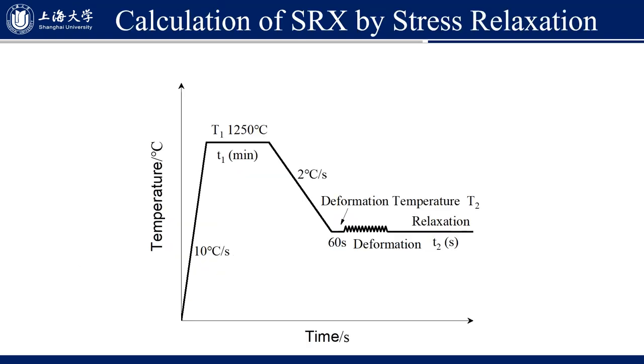Then let's discuss calculation of static recrystallization by the stress relaxation method. This slide illustrates the stress relaxation test of the steel. The steel is first heated to a temperature and then cooled to the deformation temperature. After deformation, the sample was kept at a constant temperature for different relaxation times.